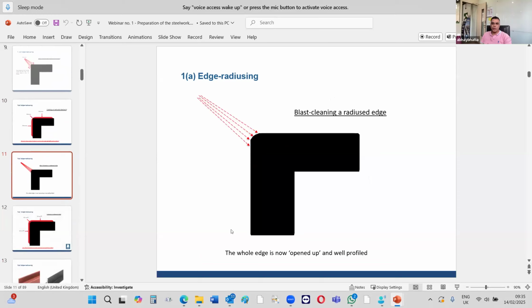So, Rick, this is a very true case. We are doing heavy fabrication, and we have seen that on channels and angles at the edges always, because they are using spray paint. The coating does not flow enough, it does not disperse enough, and if it's going to be sharp, it will never be uniform. So some radiusing is always preferred, and applying with a brush is recommended at the corners.